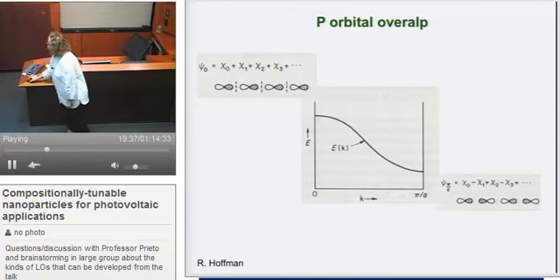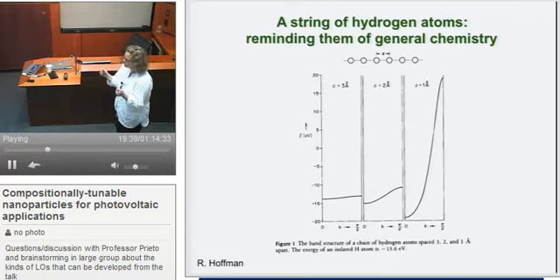So, we talk a little bit about, again, degree of overlap. And so we talk about how if you put these hydrogen 1s orbitals really far apart, there's not very much overlap. So that means that the bonding combination is not great, but the anti-bonding combination is not that bad. As you start pushing them closer together, the bonding combination is good, the anti-bonding combination is bad. And if you get them too close together, you start getting some repulsion. So the good combination is good, but it's not great, and the bad combination is very high.